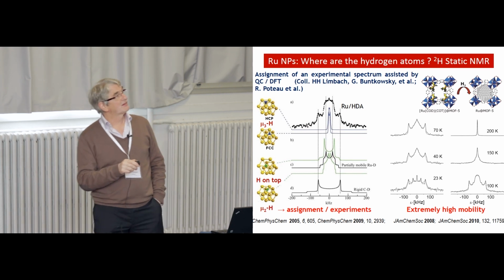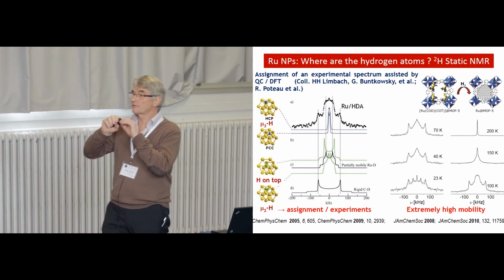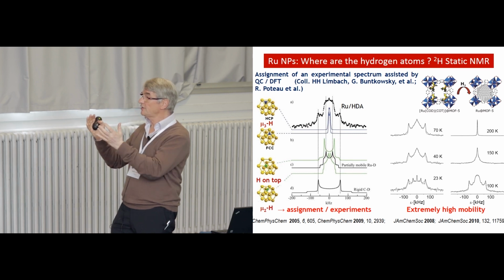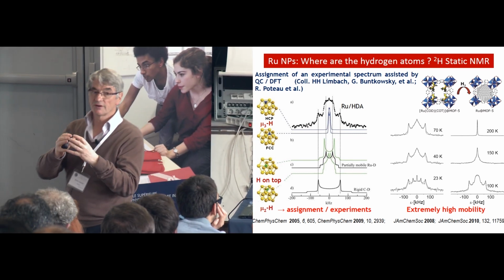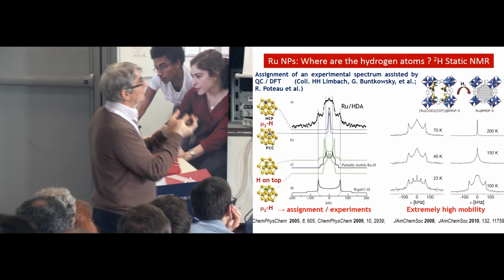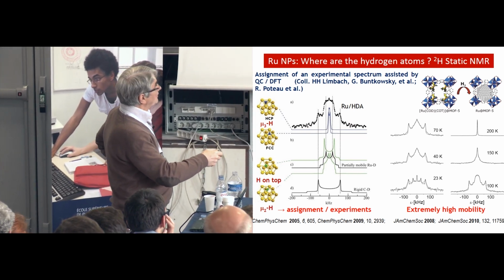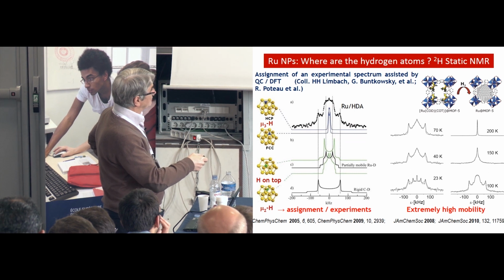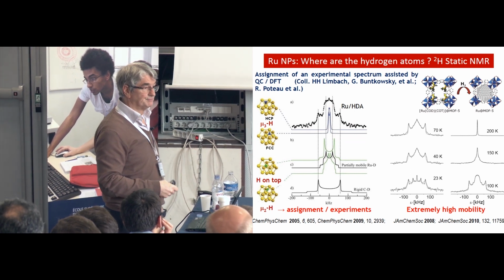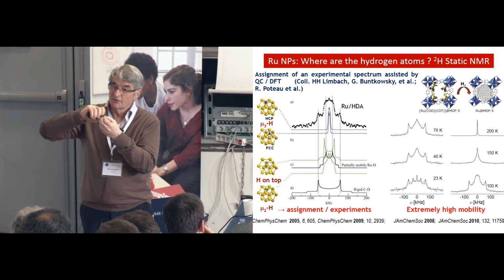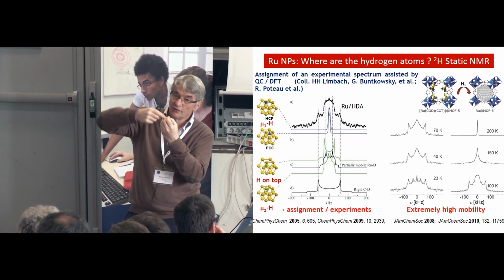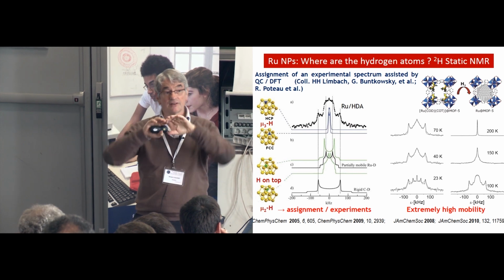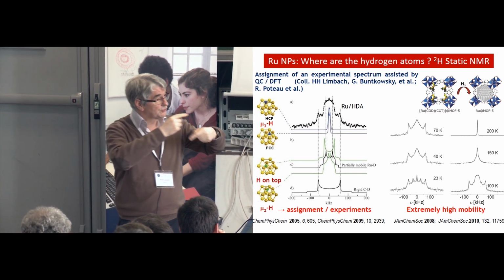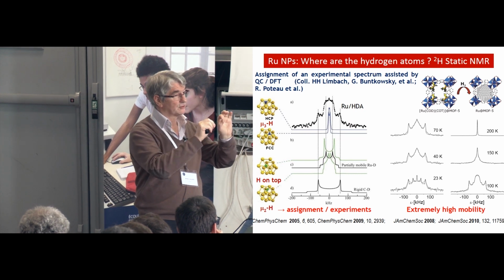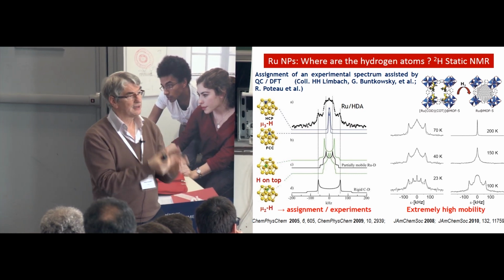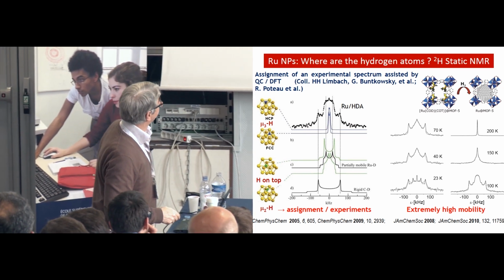In one case, where we prepared the ruthenium nanoparticle into a cage, a molecular organic framework, there is no ligand at the surface, then we could see that the hydride are dynamic down to 20 Kelvin. So at 40 Kelvin they start to move at the surface of the particle, which means that the barrier to move at the surface is extremely low. So there is a high dynamic on the surface of this particle.